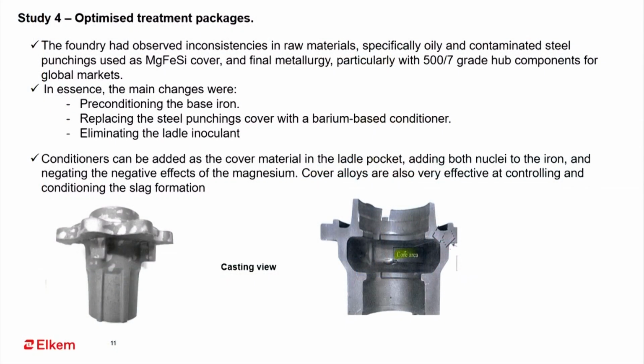And the third case is mainly this. In magnesium treatment, it is ferrosilicon magnesium, then on top of this, steel punching. That is the standard practice for the sandwich process. In this case, we maintained the other parameters almost similar, but changed the steel punching cover. In place of steel punching, we used a specially designed covering material. It contains barium, mainly barium calcium, with some other ingredients.